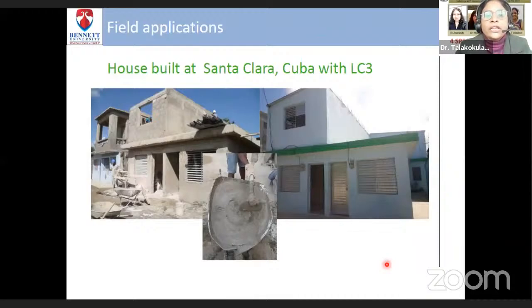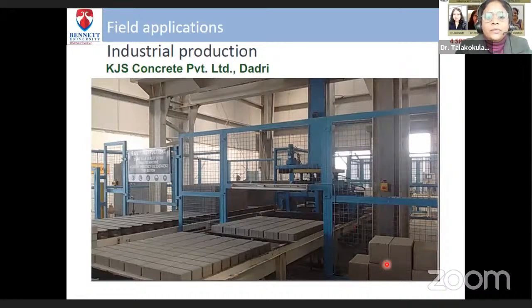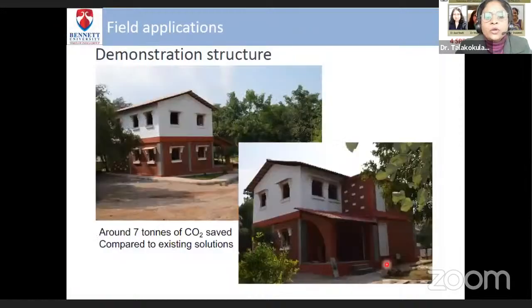And if you look into the field application of this LC3 cement, the first house has been built in Cuba at Santa Clara using this LC3 cement. In our own Dadri plant, LC3 cement blocks are being developed at KJS Concrete Private Limited. And this is a demonstrative structure which has been built using LC3, and they also did the CO2 emissions calculations and found that around 7 tons of carbon dioxide has been saved compared to the existing solutions.